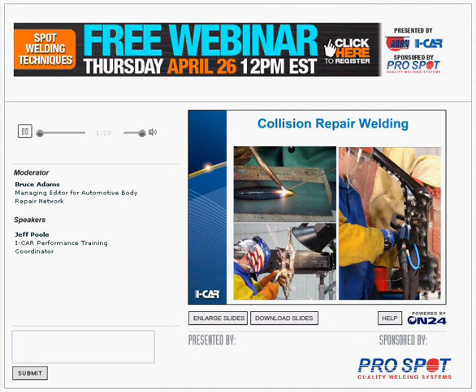Over the years, the welding processes that we've used in collision repair have changed. And one of the main influencing factors is really the evolution of the materials used in the vehicles. Construction has changed dramatically. Looking back over the history of automobiles, for the first 70 or so years, we didn't see any dramatic evolution in the material content. But then about the 70s and going into the 80s, and right around when ICAR was founded, we really started to see that transition, with the materials getting thinner and lighter, and stronger materials going in there as well.